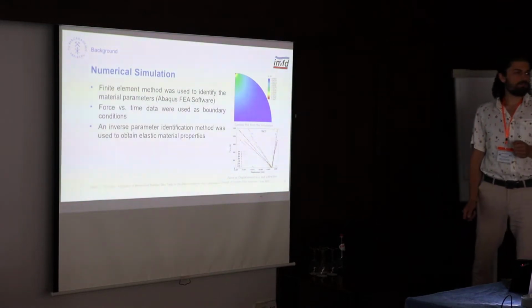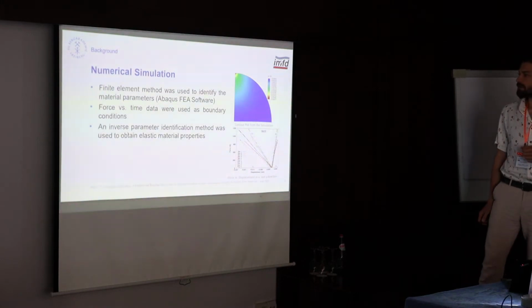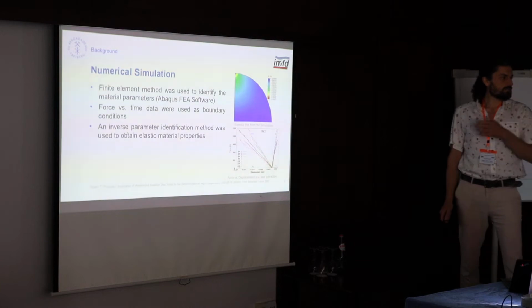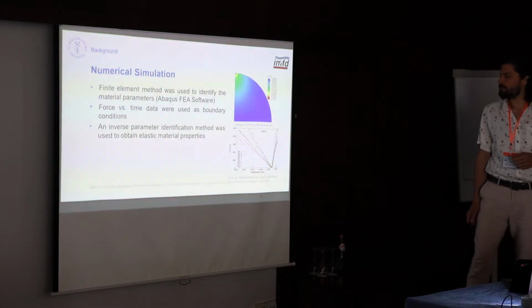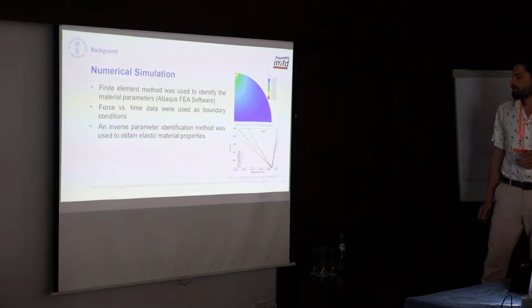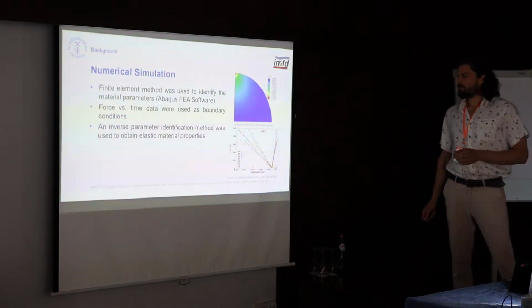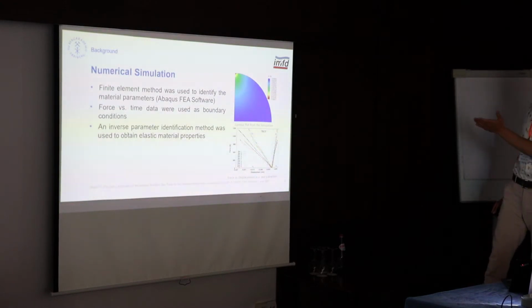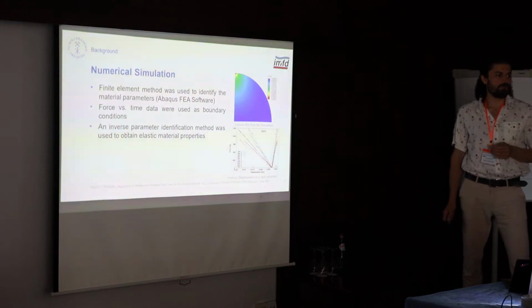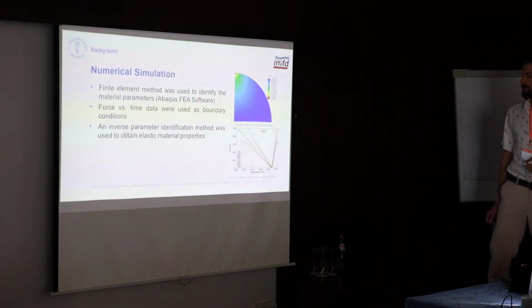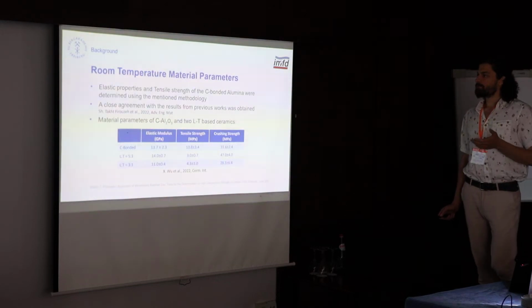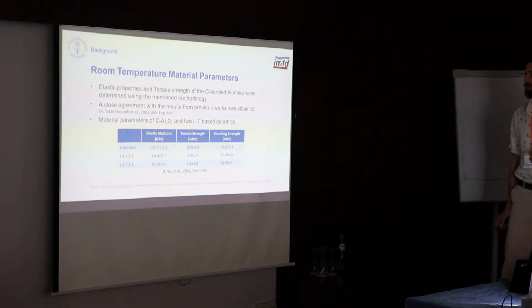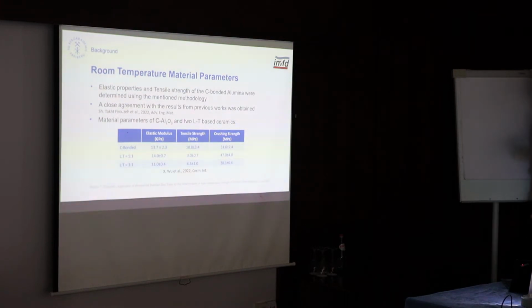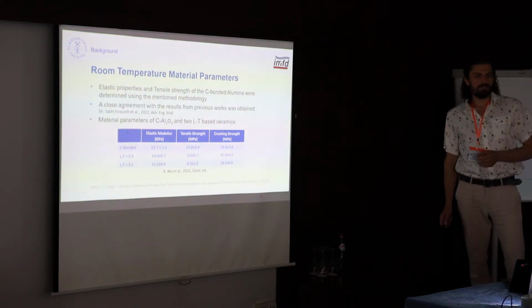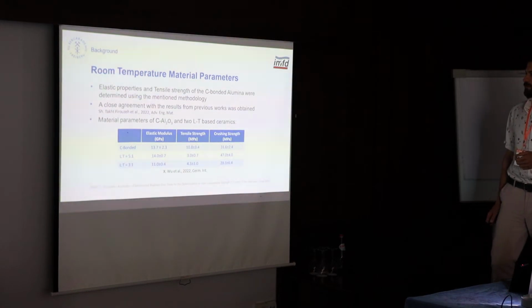numerical simulations using the finite element method in Abaqus software, and the force data from the experiment was used as a boundary condition for these models, and the rest was to do a reverse material parameter identification to bring the force displacement curves of the simulation closer to the experiments, and this gave me elastic properties of the material and tensile strength of the carbon bonded alumina at room temperature. And so I didn't go into too much detail in this work. There has been a publication regarding this work.